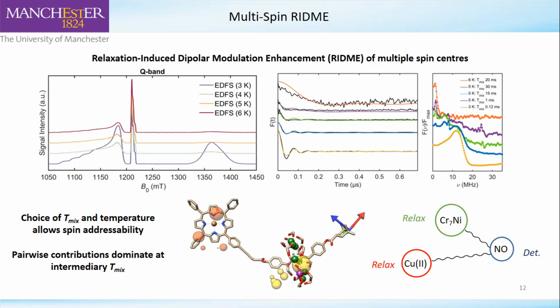and our temperatures. And what we saw was that at very low temperatures, where we have the ring signal quite present in the field swept spectrum, and we're detecting on the nitroxide with a short T-mix time, because the chromium-7 nickel ring relaxes very, very fast, we get the dipolar interaction expected for the distance between the nitroxide and the chromium-7 nickel ring. And again, we could fit that using our orientation dependent model and work out where our ring is ending up relative to our nitroxide spin.